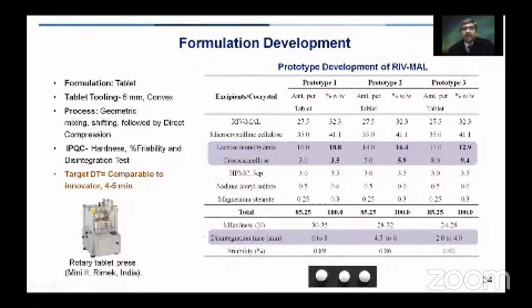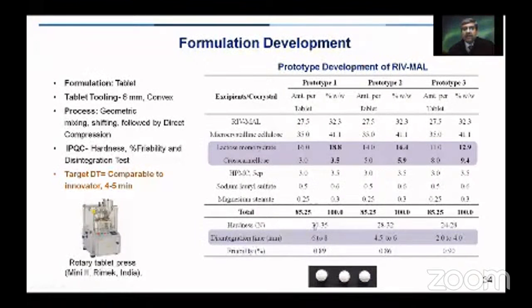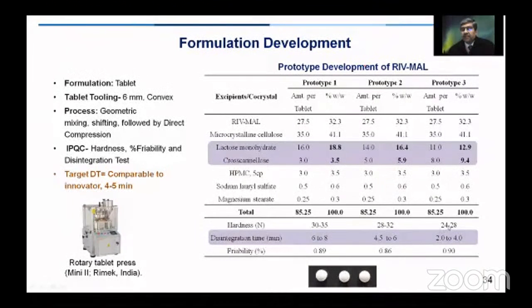These are the quality control parameters that were obtained for these prototypes. So as you can see, the hardness was well within the acceptable ranges. Disintegration time was slightly higher in this case and in this case, while it was optimal in this particular case, because we wanted a disintegration time of less than 5 minutes. The friability was acceptable in all the cases, and these are the tablets that were obtained for these 3 prototype formulae.